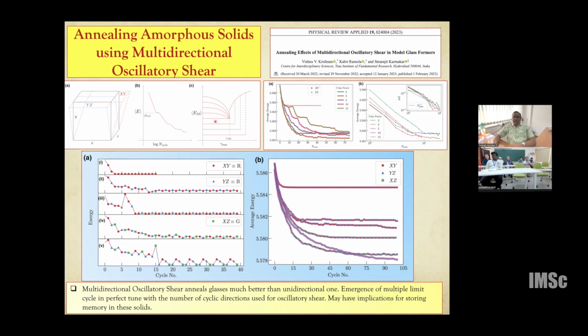But what we looked at in addition is that instead of doing an oscillatory shear along one direction, let's say in the XY plane, we introduced oscillatory shear along other possible directions. Particularly in 3D, you can have XY shear, and you can have YZ and ZX. What we found is that if you do an XY oscillatory cycle, then the energy reaches a steady state. Then you switch your direction and do YZ, then the energy decays once more and reaches a plateau. And from there, if you do XZ oscillatory shear, then you can further anneal.